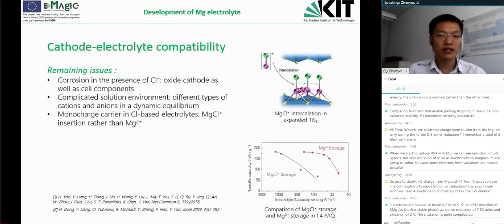And on the other hand, we also have a complicated solution environment with dynamic equilibrium in the chlorine-based electrolyte. As shown before, we have a couple of these magnesium chloride cluster species, and this monocharge carrier has a possibility even to intercalate into the system as a whole rather than the double charge carrier. And as reported before, the magnesium chloride storage, if we have this scenario, then we might need more electrolyte if we want to achieve the same specific capacity as in case of this magnesium ion storage.